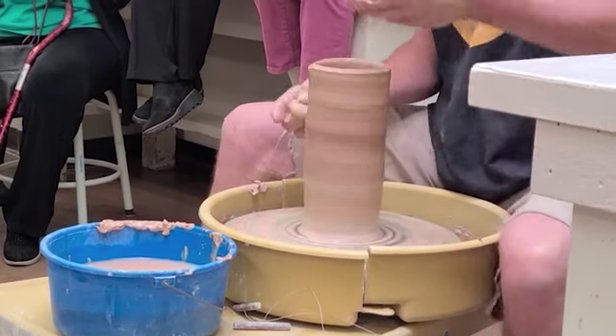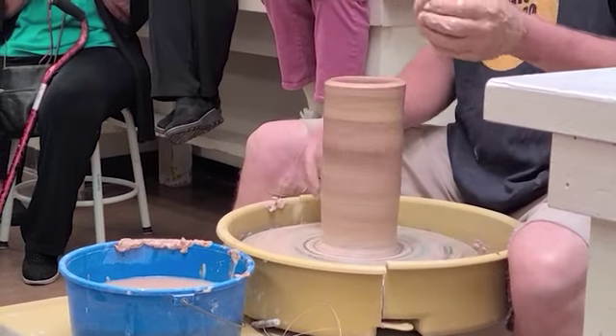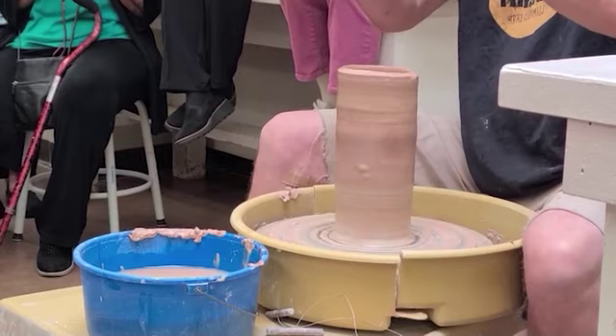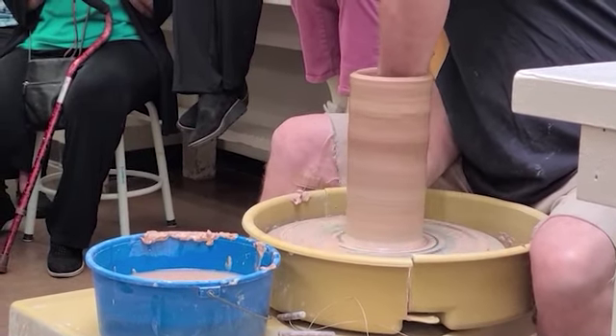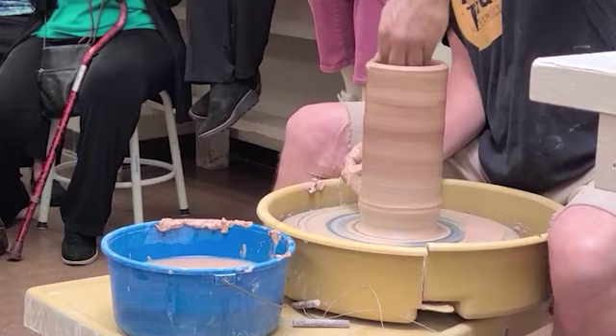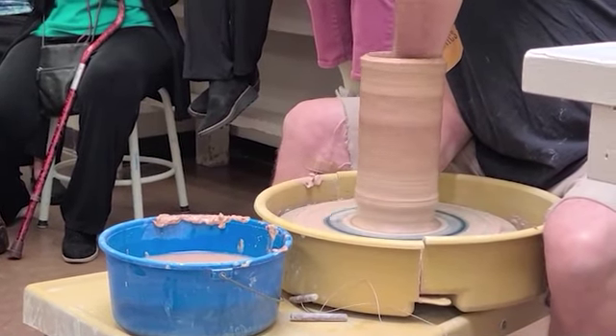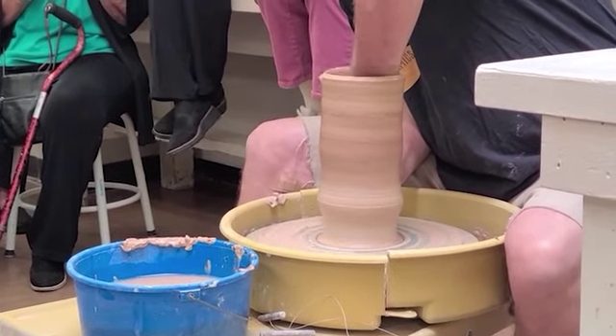And then what plagues most potters is their pots are heavy at the bottom. So the trick to that is you want to go in, you want to get that clay pushed up the wall. So I'll push out with my outside hand and then I'll grab that chunk of clay. So it makes a little lump on the bottom. And if I'm on the inside, I can feel a groove right there. And then I'm just pinching that groove and bringing it up the wall.